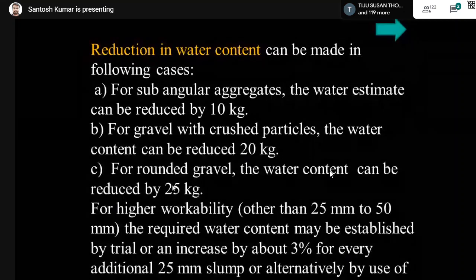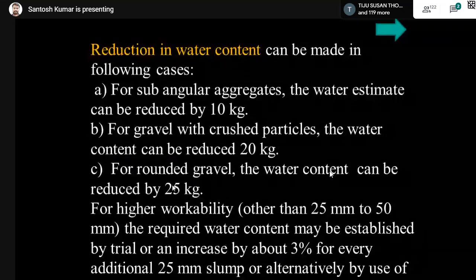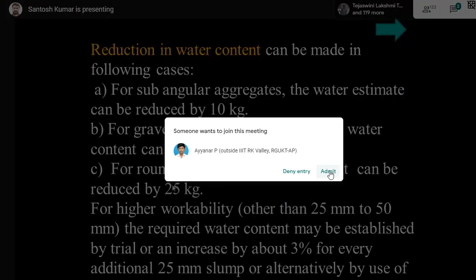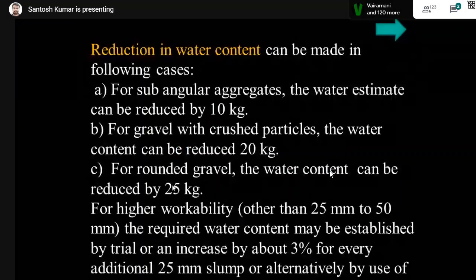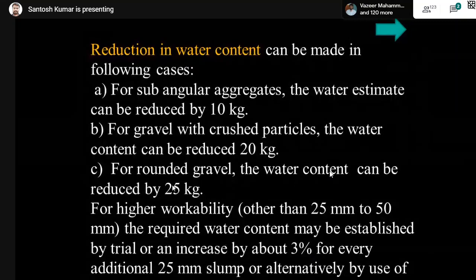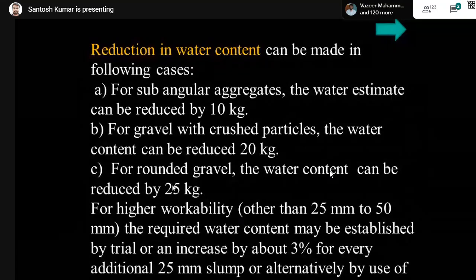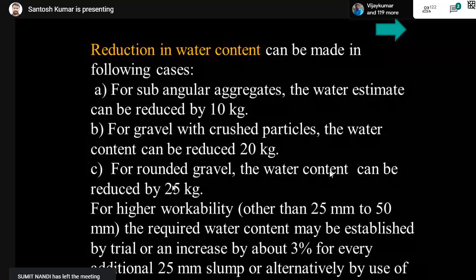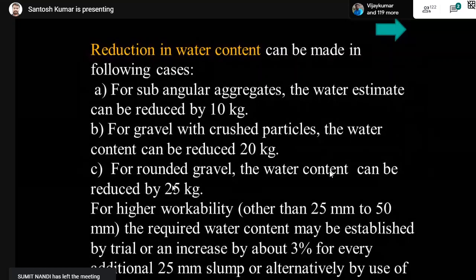And for higher workability, other than 25 to 50 mm, the required water content may be established by trial and error, increasing by 3% for every additional slump increment of 25 mm. Same applies when you want a lesser slump also; you have to reduce by 3%. If you want an additional 25 mm slump, you increase water by 3%. If you want 25 mm less slump, you reduce water by 3%.